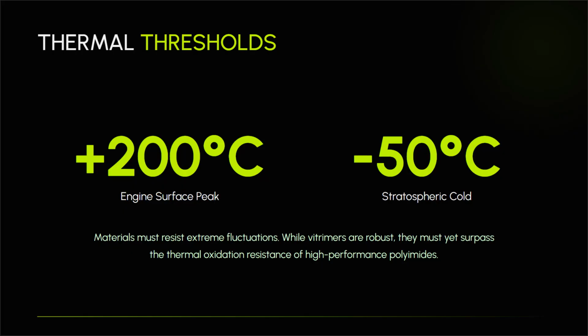Moving on to thermal and environmental thresholds. As established in recent literature, aerospace composites must endure extreme temperature fluctuations. This ranges from the freezing cold of approximately -50 degrees Celsius at cruising altitudes in the stratosphere, up to over 200 degrees Celsius near engine components and localized friction zones. Currently, the thermal and oxidative resistance of most Vitrimer systems does not yet surpass that of conventional, high-performance aerospace polyimides.